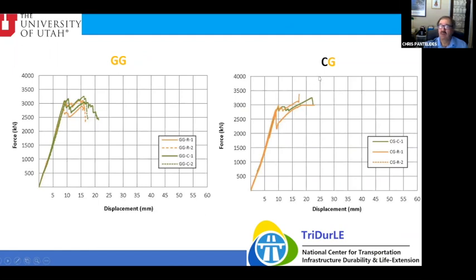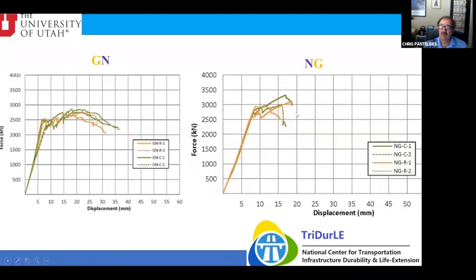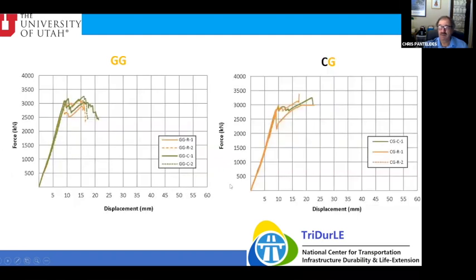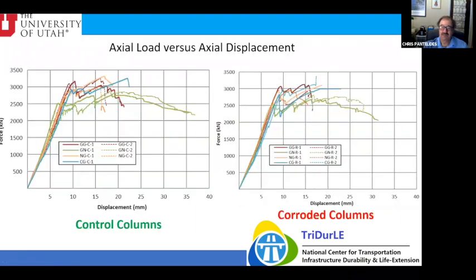And this is the one with the clad vertical and the fiberglass spiral. And again, we see a little bit of influence of the corrosion, but definitely these three types with the fiberglass spiral barely reach 20 millimeters of axial displacement, whereas the one with the stainless steel spiral reaches almost twice that. So the displacement capacity of the stainless spiral is very obvious.